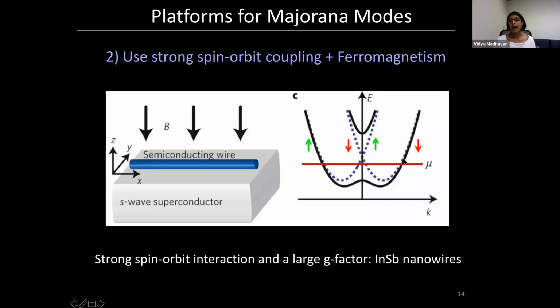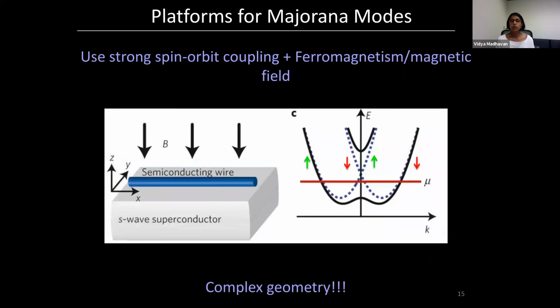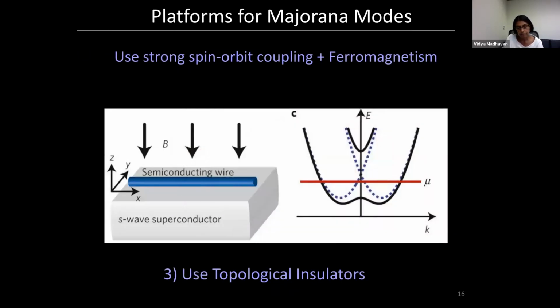And moreover, this band has a very well-defined spin. So if you can engineer the system to have a band structure like this, and then you put this semiconductor on top of a superconductor, you open up a gap on just this one band, then you get Majorana fermions at the end. So you can see just from my description that this is very complicated to do. And in fact, because this is so complex, many of the experiments on such systems have been done with transport, and it's been really difficult to do STM experiments on these kinds of nanowires.